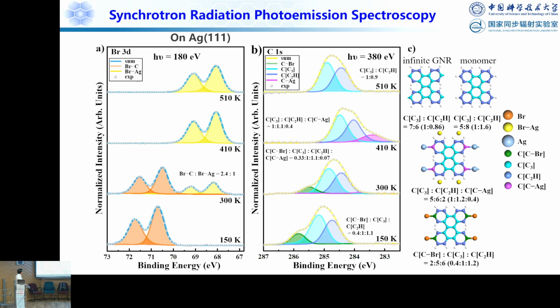When the molecules stay intact, this is the bromine peak located here, and then you have three carbon peaks, which can be assigned to the carbon atoms with different chemical environments here, and the ratio is quite consistent with the stoichiometric ratio. When you increase the temperature, you form the carbon-organometallic species on the surface. You find this new peak here, and at this temperature when you form only the organometallic intermediate on the surface, we observe this peak, which is again quite consistent with what the stoichiometric ratio should be. And if you go to a higher temperature, when you form the porous graphene nanoribbon, you only have these carbon atoms here. Okay, so this really helps to understand the STM result.